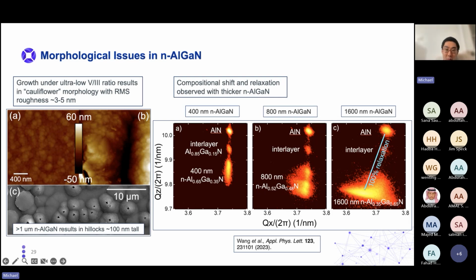So in terms of what's going on in the material, this is reciprocal space mapping of the material. So with 400 nanometers of n-type aluminum gallium nitride, you can see the aluminum nitride, and our interlayer, which we grow on, the buffer layer between the n-type aluminum gallium nitride and aluminum nitride, because our n-type material is 65% aluminum, and it is too far from the aluminum nitride in terms of composition. So we add this interlayer to smoothen out the 65% material. And as you grow thicker to 800 nanometers, this material actually starts drifting in composition.